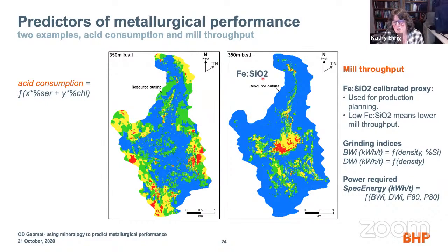And for mill throughput at a local sense or on a short-term scale, we use simple things like an iron silica ratio. An iron silica ratio is really a reflection of the weight percent of hematite to the weight percent of sericite plus the silica content of sericite and quartz. And it's really a calibrated proxy. And we know we get into trouble when the iron silica ratios are low, and that also means that our mill throughput's going to be low. So it's something that's assayed in the process plant all the time, and so they can keep track of what's going on.